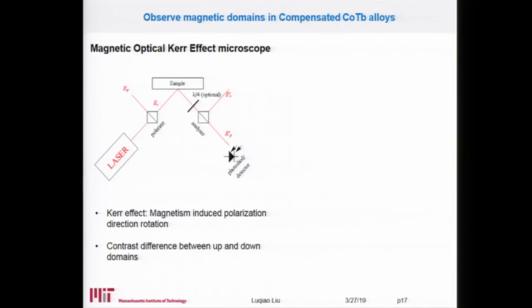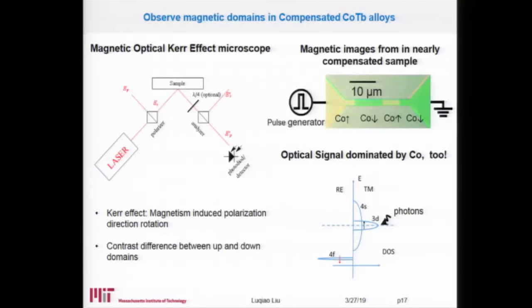So through that rotation of the linear polarization, we can know whether the magnetic moment is pointing up or pointing down. So actually, by utilizing a magneto-optical Kerr effect microscope, we can clearly see the domain structure inside a micron-sized sample. This is still cobalt-terbium alloy with its moment close to zero, but you can still see that there are brighter or darker domains. The brighter domains correspond to cobalt pointing up, and the darker domains correspond to cobalt pointing down. Again, here, similar to the transport measurement, the optical signal is also mostly dominated by cobalt.